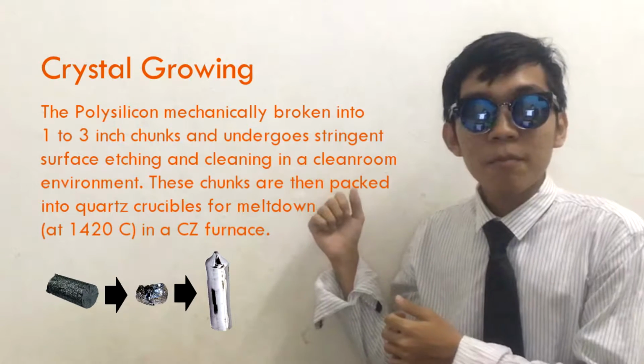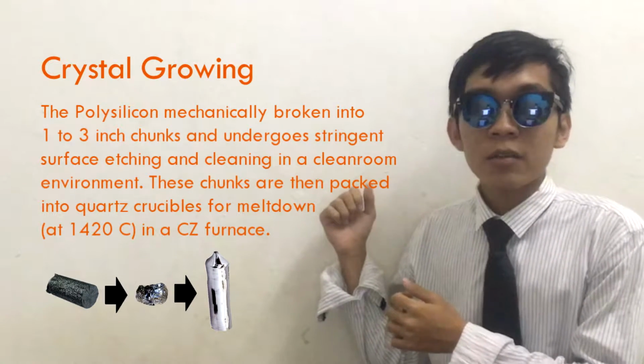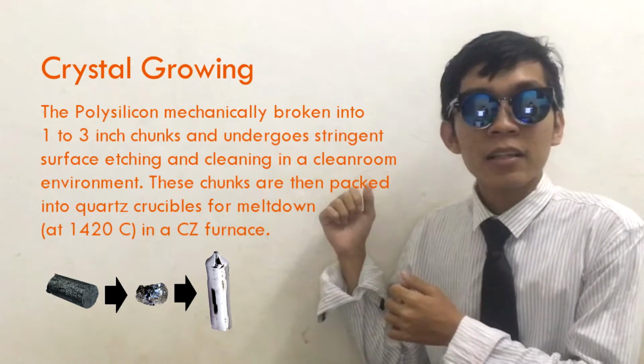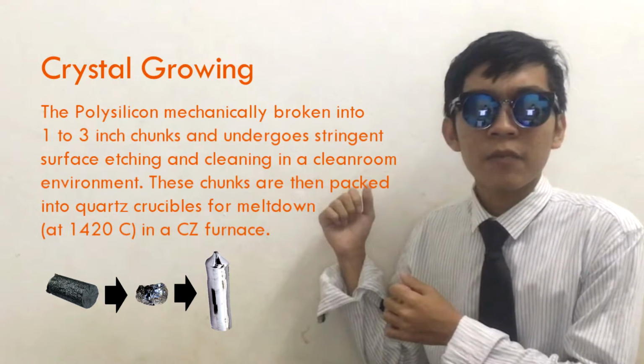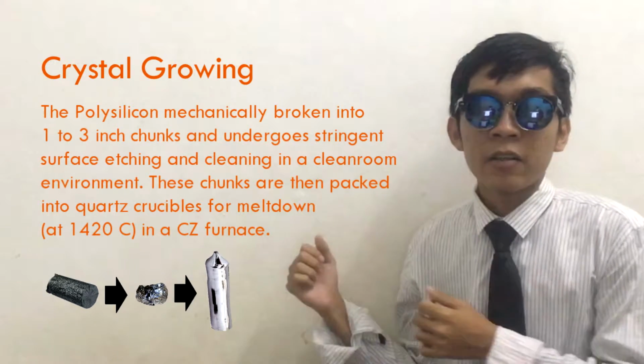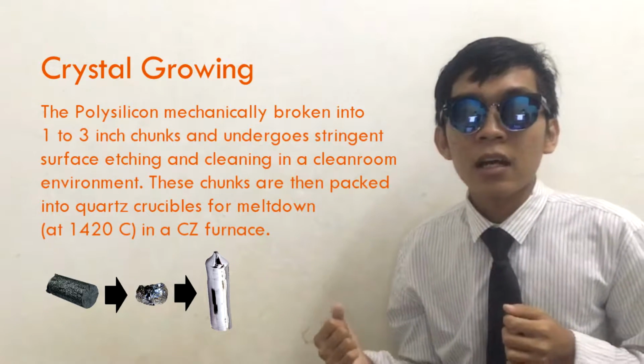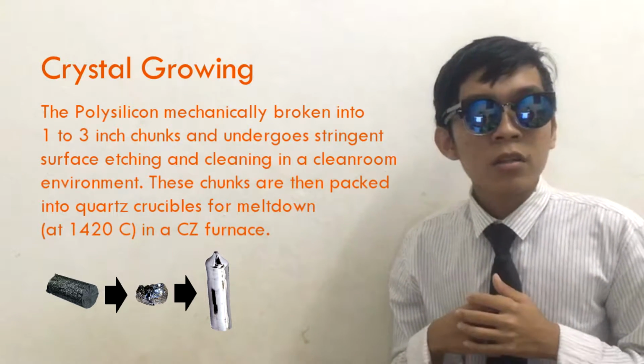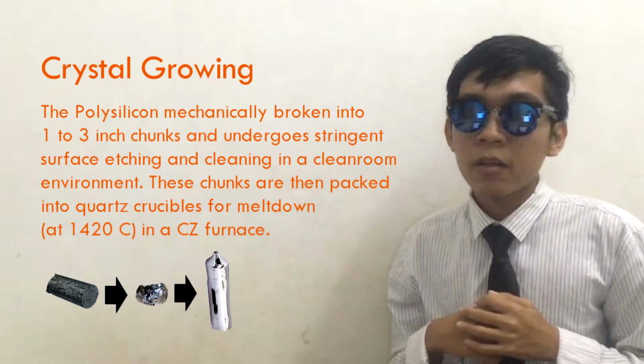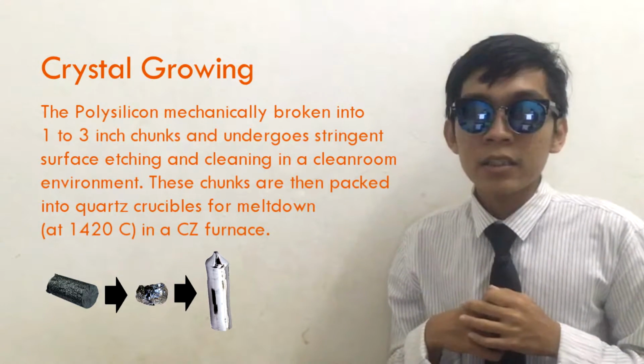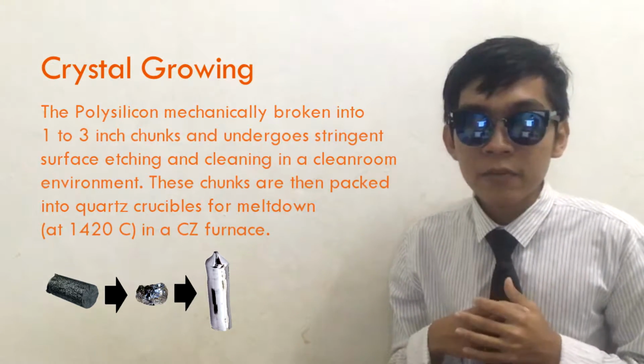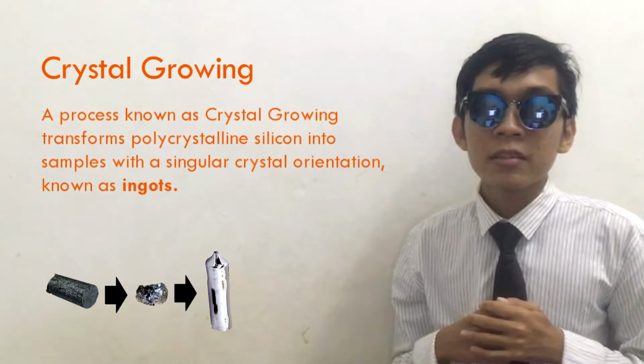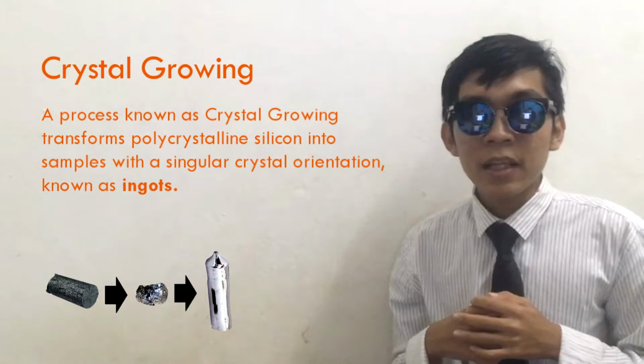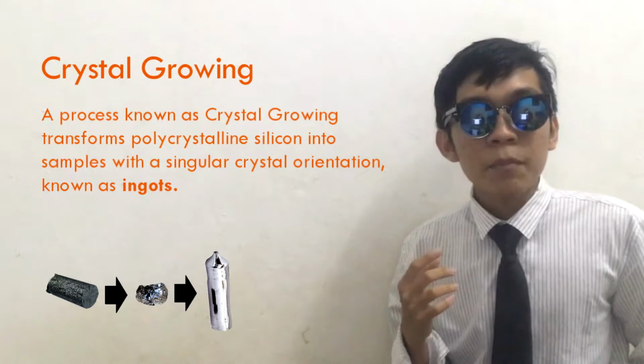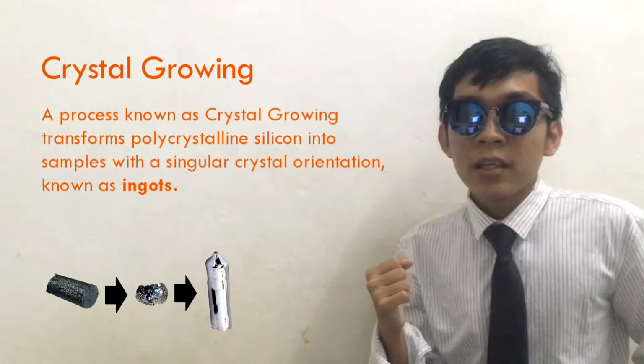The polysilicon is mechanically broken into 1 to 3 inch chunks and undergoes stringent surface etching and cleaning in a clean room environment. These chunks are then packed into a quartz crucible for meltdown at 1420 degrees Celsius in a furnace. A process known as crystal growing transforms polycrystalline silicon into samples with a single crystal orientation, known as ingots.